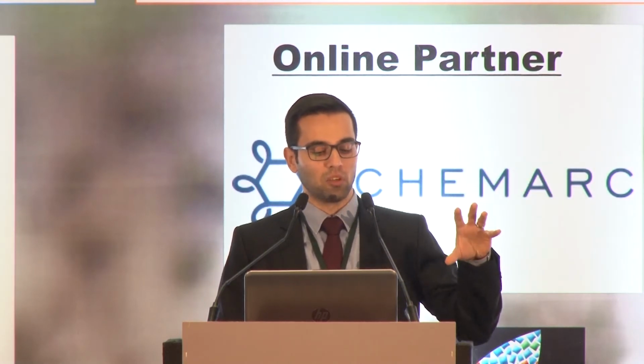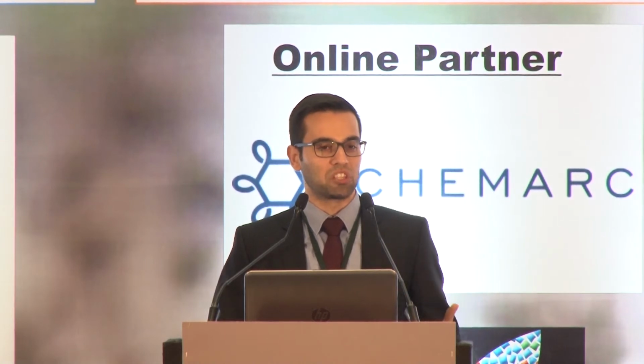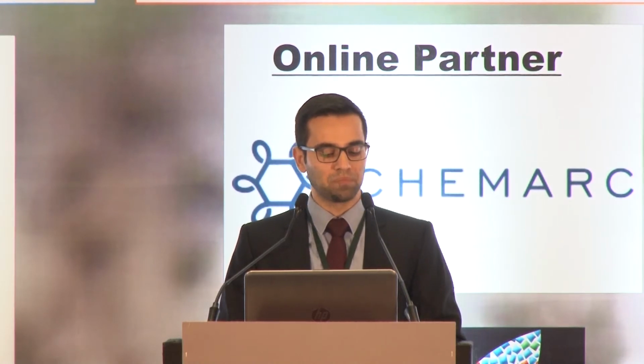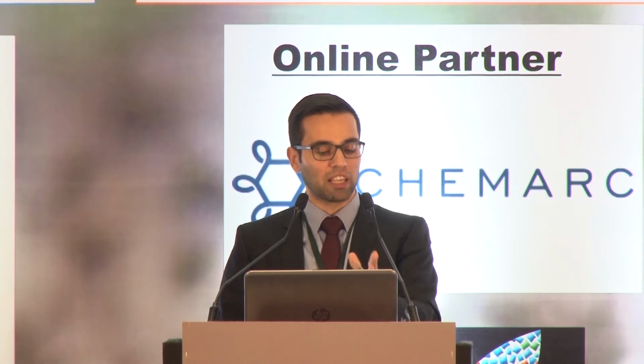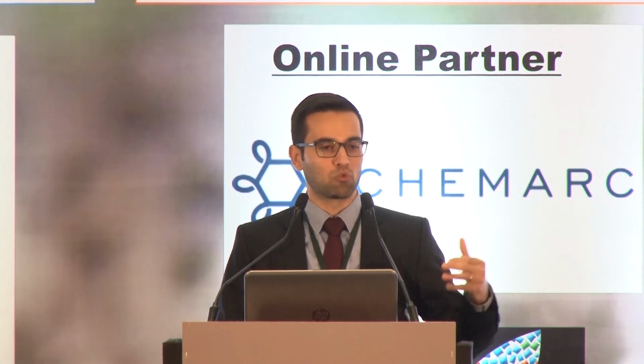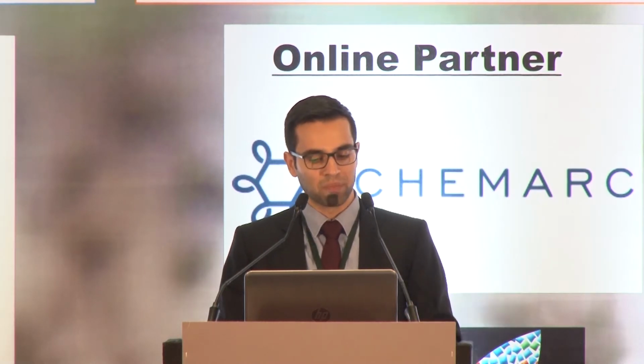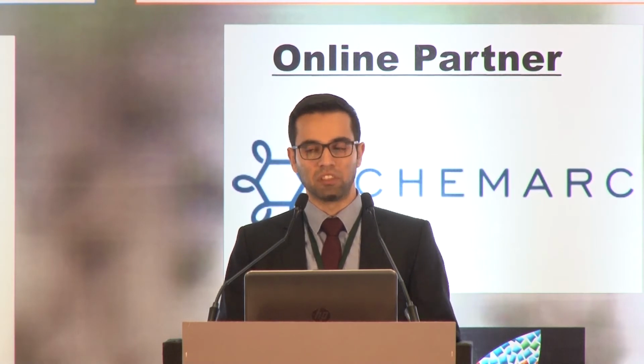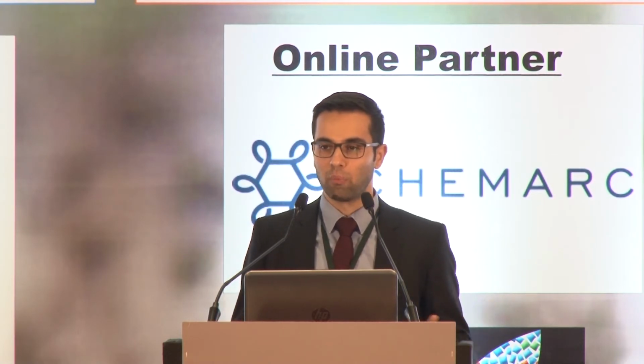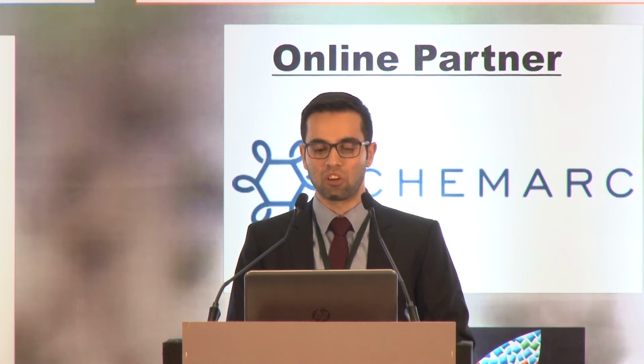And in that case, we took here only the surface area, BET, square meter per gram. And you see, if you need high elongation at break, you should get filler with low surface area. This is logical. But then you say, okay, it's very simple. We don't need to do a high-tech development. We can get any filler with low surface area.